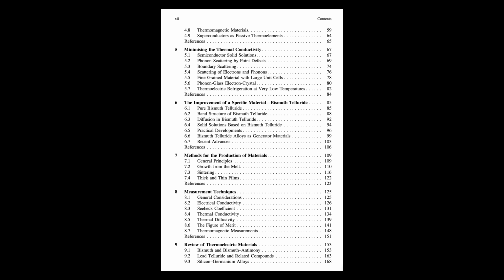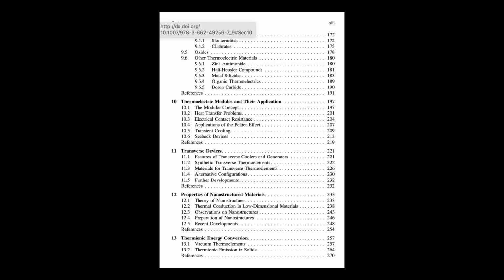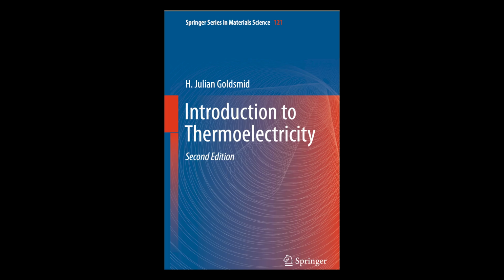Okay, last topic, thermionic energy conversion. How is that different from thermoelectrics? Thermionics is a different beast. Instead of charge moving in a solid, you use heat to boil electrons off a hot surface, the cathode, into a vacuum. They travel across the vacuum and are collected by a cooler surface, the anode, creating current. The appeal: no solid material for heat to conduct through, potentially higher efficiency. But you need emitters with really low work functions, the energy needed for electrons to escape. For cooling, you need even lower work functions.